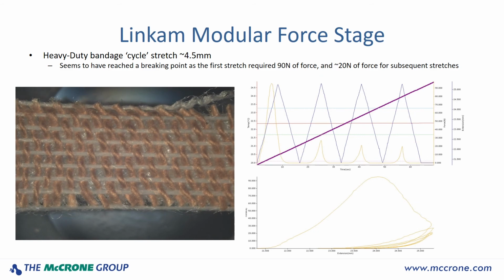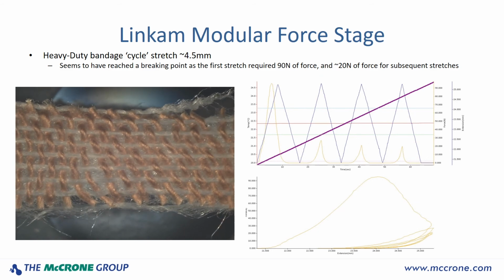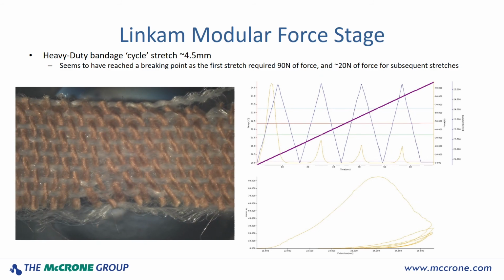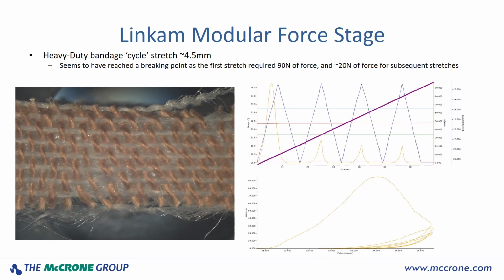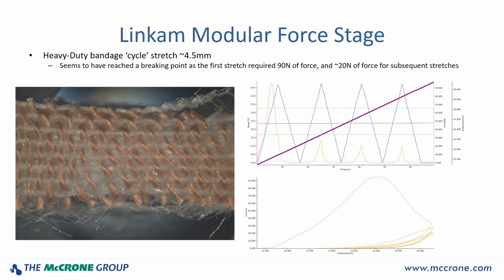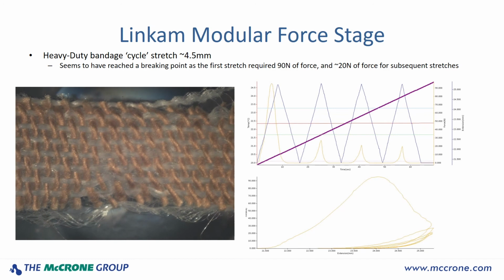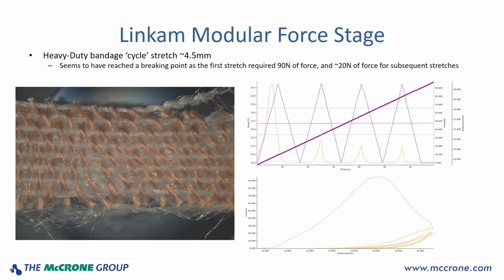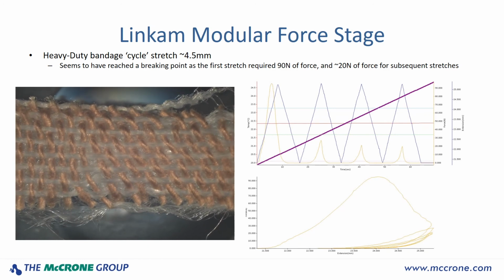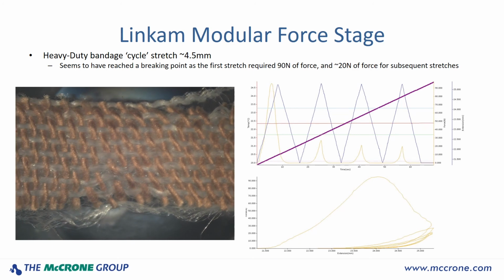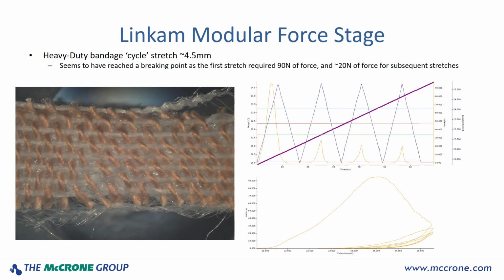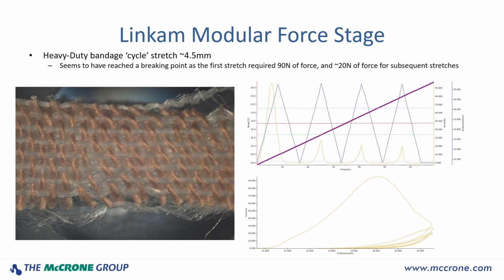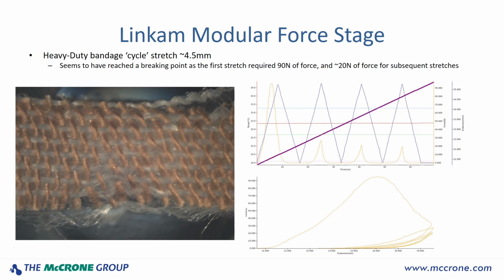The second test for the heavy-duty bandage was the same 4.5 millimeter cycle that we did for the waterproof bandage, and once again results were similar. There was a large force required for the initial stretch, and it seemed to reach a breaking point, which led to much less force being required for subsequent stretches. For the initial stretch, it required a full 90 newtons of force, and then for stretches afterwards, it only required roughly 20 newtons of force.